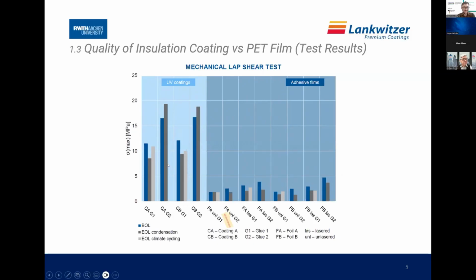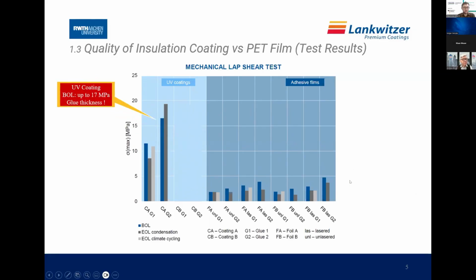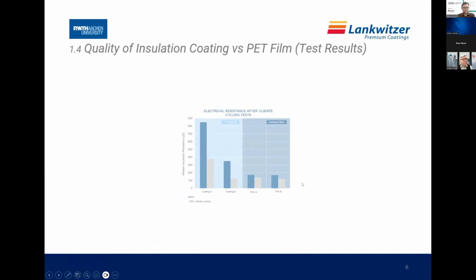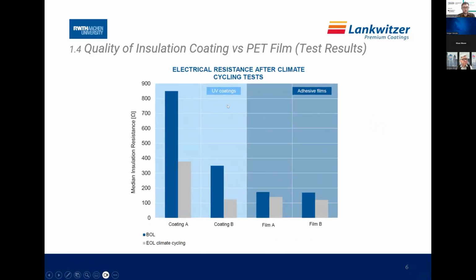To the left, we see the UV coatings in terms of mechanical lap shear strength, and to the right, the adhesive films. So up to about 17 on the left on the coatings and barely nothing on the adhesive films. Last one. Similar is the electrical test after climate chamber. To the left, you see the UV coating. To the right, you see the adhesive films. So massive difference, beginning of life, end of life, beginning of life, end of life.